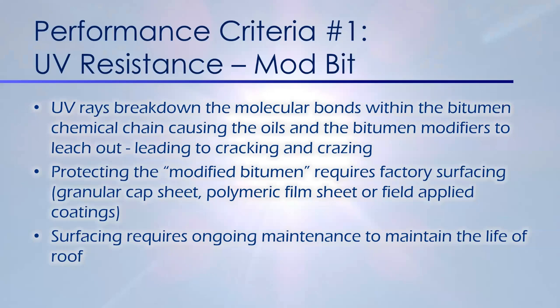When we look at modified bitumen, because it is a bituminous process and it's a factory created sheet of those multiply systems, the results of UV are very similar. The UV rays do break down the molecular bonds within the bitumen, causing the oils to leach out. That can also lead to cracking, crazing, and alligatoring on the roof.